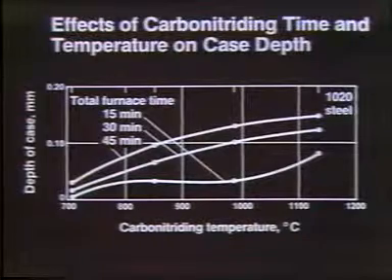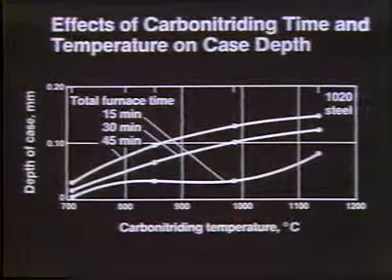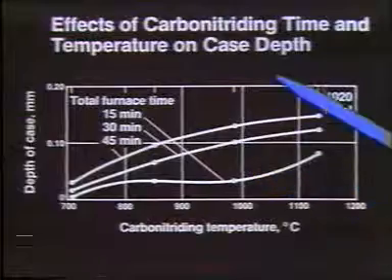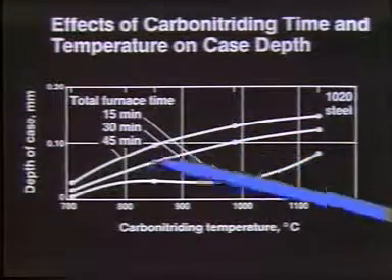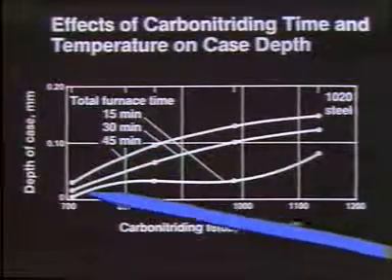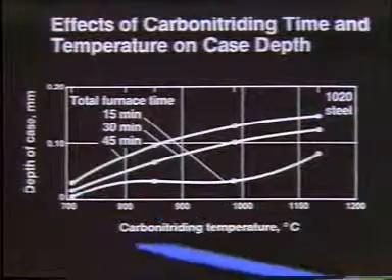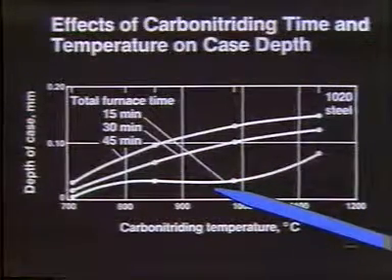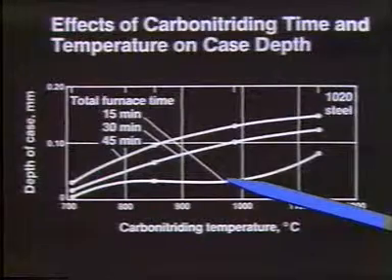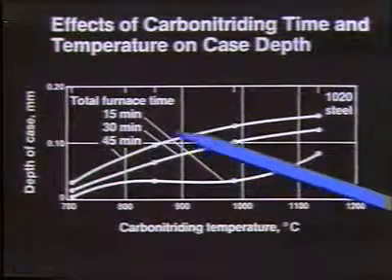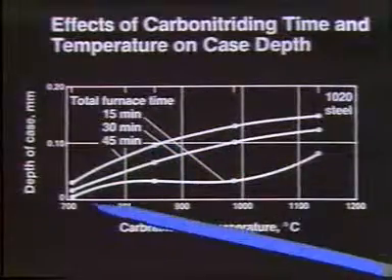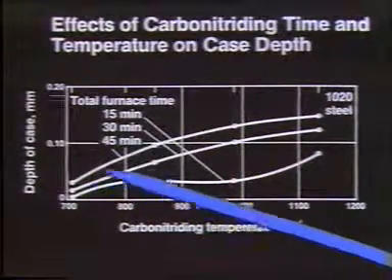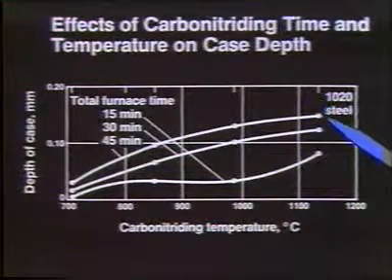If we look at carbon nitriding and look at the depth versus temperature for 1020 steel for various times — and this is a situation for liquid carbon nitriding in a cyanide solution — we have a 15-minute treatment, a 30-minute treatment, and a 45-minute treatment. The depth of the case increases rather radically as we change the time. For a 45-minute time in the bath, we have quite a nice depth of penetration of the case for this particular material.